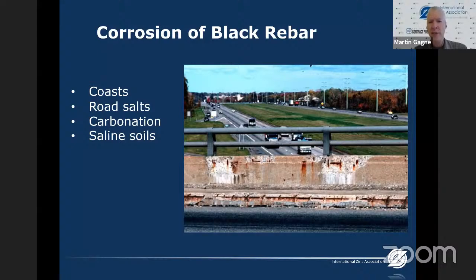Now, the corrosion products of iron can take up 7 times the volume of the iron itself. So this is what puts pressure on the concrete. Concrete is very good in compression, good compressive strength, but very poor tensile strength. So when we put a lot of corrosion product build up around the rebar, that puts tensile stress, which causes the cracking and the spalling. Now, the chloride can come from the coasts. In this case, in North America, it's from road salts, the carbonation front that can decrease the pH of the concrete, but also saline soils.